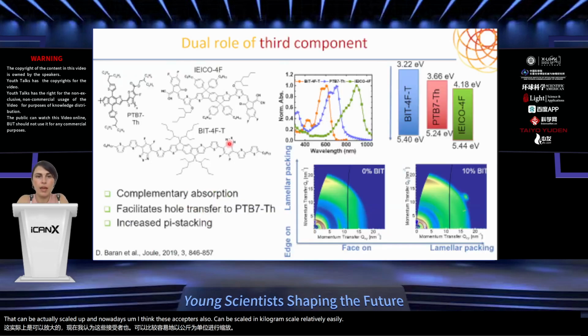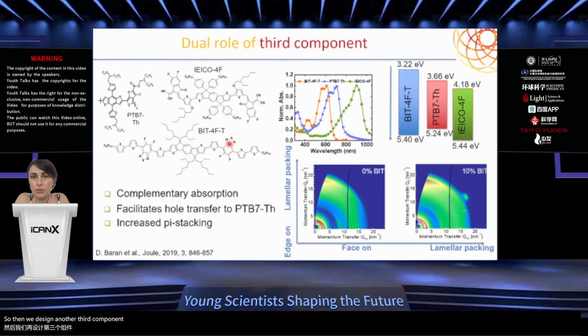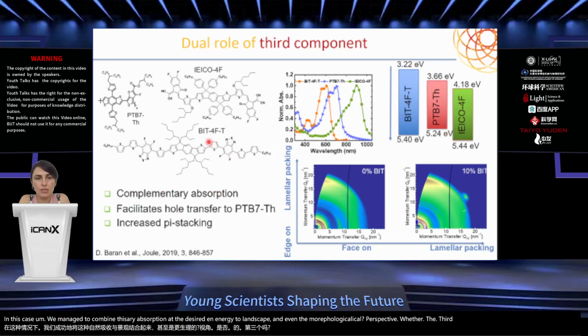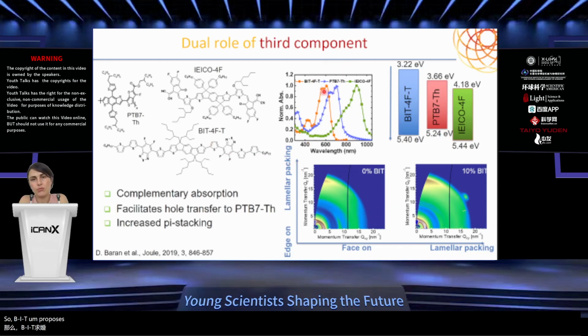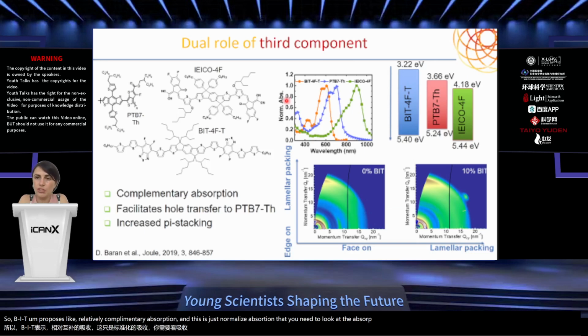So then we designed another third component because we wanted to boost the performance, obviously, and see where we can get to with the material design from a scientific perspective. In this case, we managed to combine complementary absorption, the desired energetic landscape, and even the morphological perspective with the third component, which is BIT4F-T in this case. BIT4F-T proposes relatively complementary absorption, and this is just normalized absorption, so you need to look at the absorption coefficient, and the morphology, as I said, where you can increase the pi-pi stacking when you add this third component.